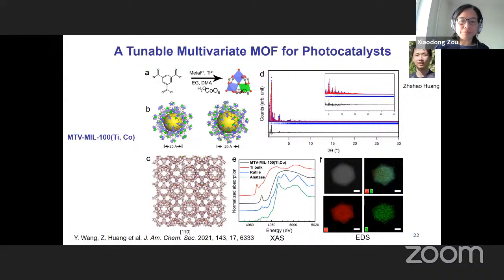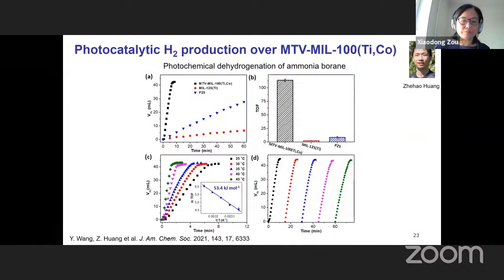Another example is tuning the metal clusters, and this is a titanium cluster. So you can combine the titanium cobalt cluster and the titanium cluster into one MOF. It's called MIL-100. This is a very complicated structure, so you can see there are cages, pores like 29 Angstrom and 25 Angstrom, two different types of cages. By doing this, we can tune the photochemical properties. So the hydrogen production is very much better compared with the untuned one, and also even better than the normal photocatalyst, P25. And it also can be recycled.